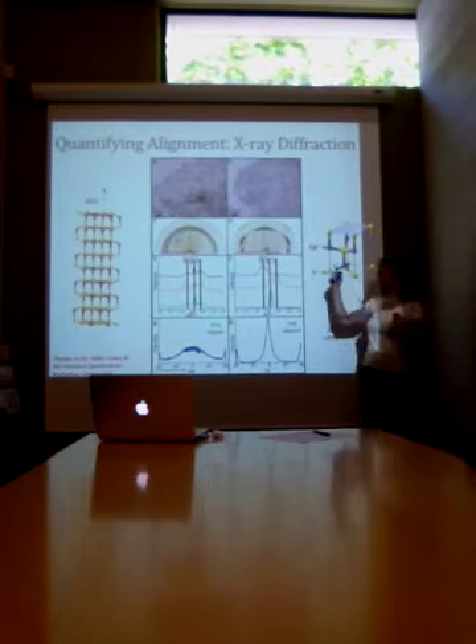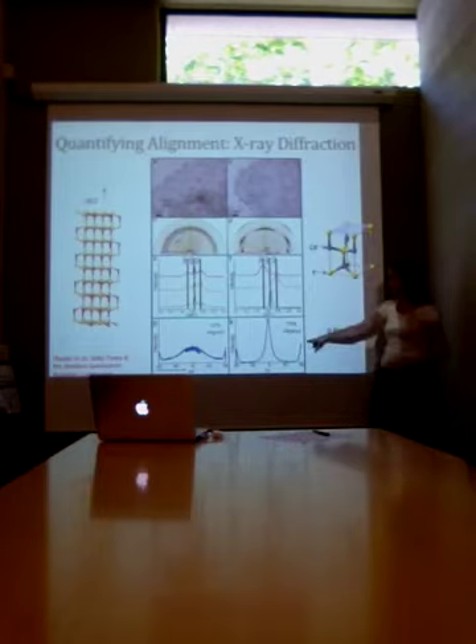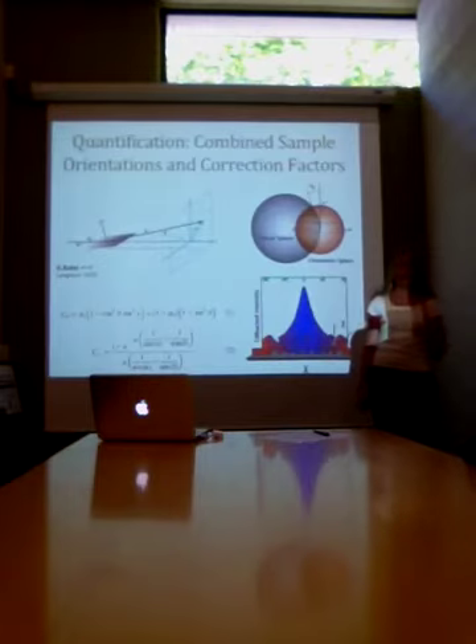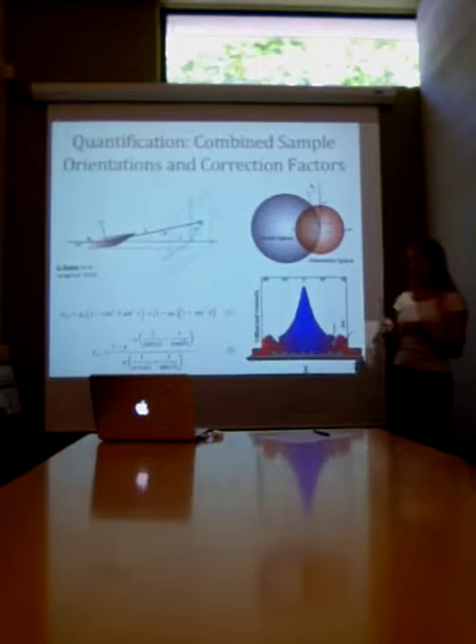And so we can turn these into histograms of how many rods are oriented at each angle. And what we see is in the case of unaligned rods, the histogram is rather flat. And in the case of aligned rods, we have a sharp peak at 0 degrees, or perpendicular to the substrate, and smaller peaks laying flat against the substrate. And we can see that the rods don't like to do much of anything in between there. The fundamental concept behind this method is elegantly simple, but quantifying it makes the details appear, and they're very complex.